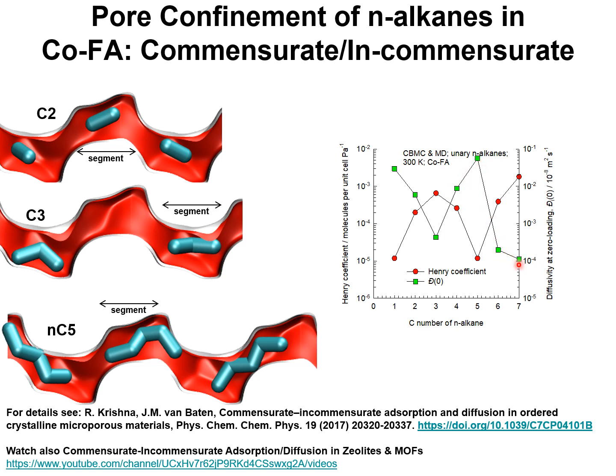Therefore, the non-monotonic behavior of the diffusivity with respect to chain length can be understood in terms of the snugness of it within a channel segment, the commensurate, incommensurate nature between the length of the molecule and the length of a single segment or two segments. For further details, have a look at my publication of 2017 and also watch the video on commensurate, incommensurate adsorption and diffusion